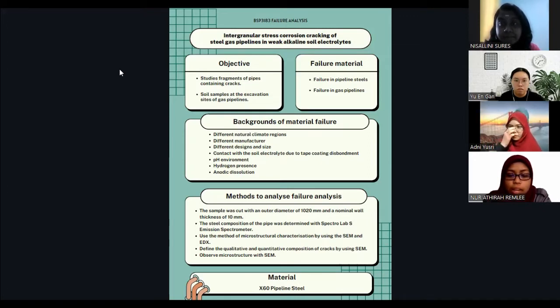Next is the contact of the pipeline with the soil electrolyte due to tape coating disbondment, and the pH of the environment that will be harmful to the pipe. Furthermore, the other background factors of the material failure are hydrogen presence and anodic dissolution. For the method of failure analysis, the sample was cut with an outer diameter of 1020 millimeter and a nominal wall thickness of 10 millimeter.